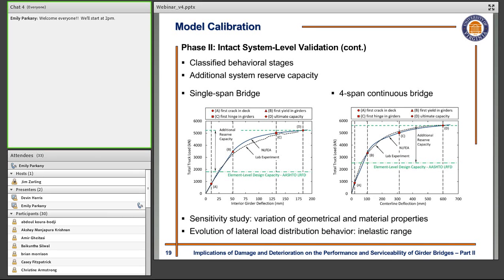Other than that, we defined the element level nominal design capacity for these specific structures based on the actual LRFD specification, and we plotted those values as the green lines in these graphs. So if you compare the ultimate capacity of these two superstructures that we achieved from the numerical analysis, or also the corresponding values from the experimental program, you can see in both of these structures we have a significant level of additional reserve capacity over the design level. So that actually confirms the complex interaction between the components and the redundancy that we have in these systems.